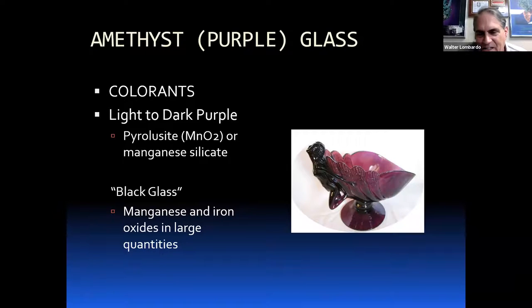Of course, the other thing to keep in mind is, glass itself is about 70% quartz, basically, in its composition. So it's not surprising that these elements have the same effect on glass. Anyway, if you want to make a light to dark purple, you can use pyrolusite, which is basically manganese oxide, or a manganese silicate. Most people have used manganese silicate as far as cabbing it, because it's basically rhodonite, which we usually see as kind of a pink color. But if you add it in a pure form, manganese silicate, you'll end up with a light to dark purple.